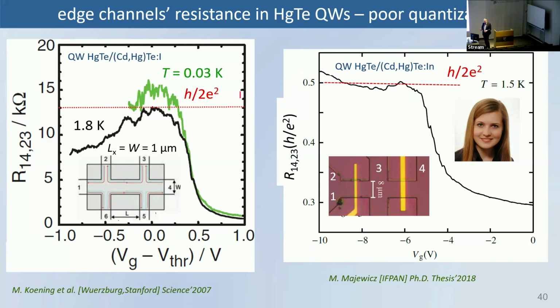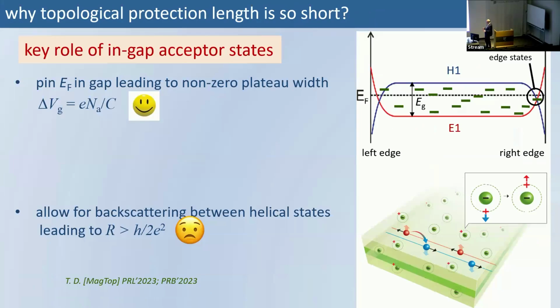Why do we not observe this quantization in this case? And the reason is impurities, which, as I mentioned, are very important in the quantum Hall effect to keep the Fermi energy within the gap. But here, although they are important in that they keep the Fermi energy within the gap, you can scan the gap because you have this impurity which pins the Fermi energy.